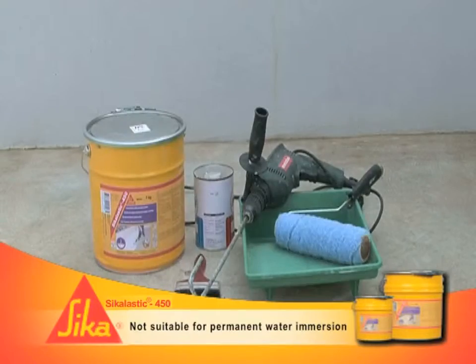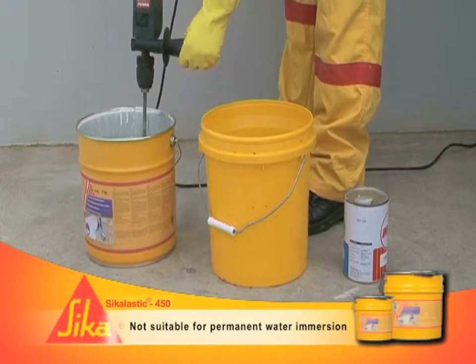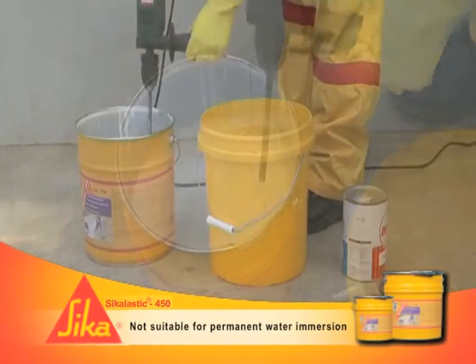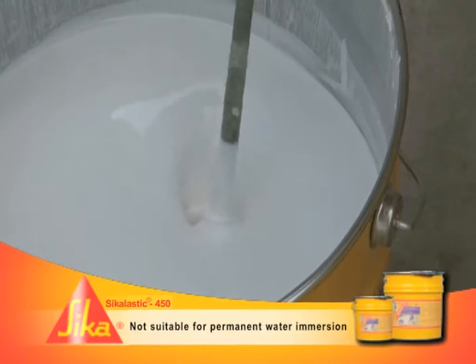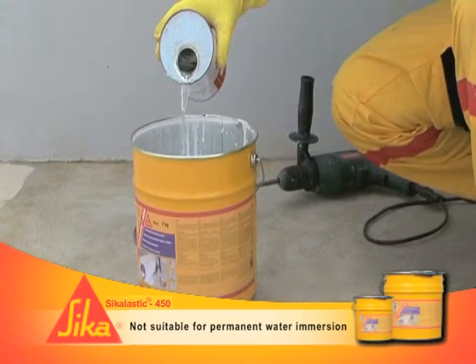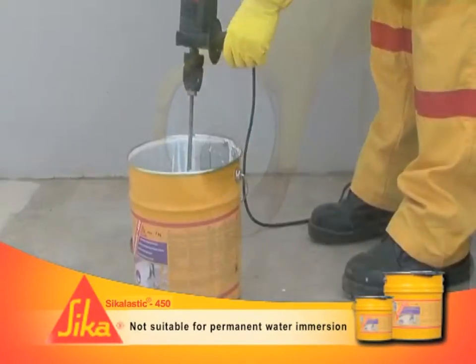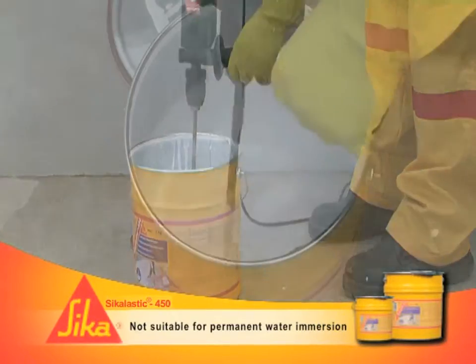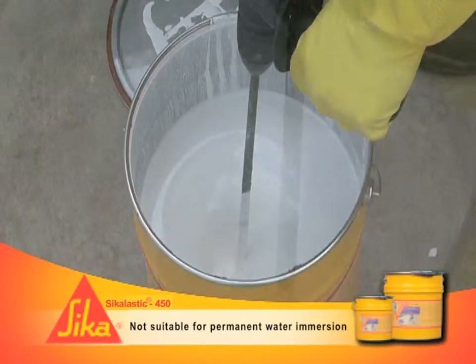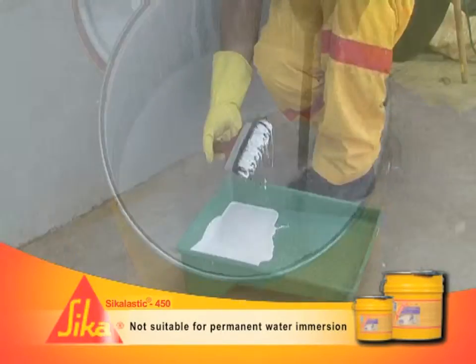Stir Sikalastic 450 thoroughly for 3 minutes. For priming, mix Sikalastic 450 with 15% thinner C. Apply on the detail areas first. Then apply primer coats by using a brush, roller, or spray.